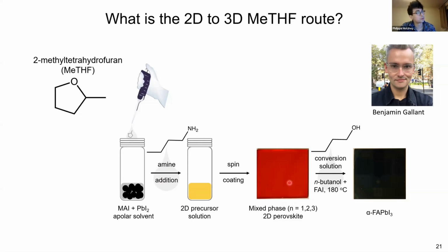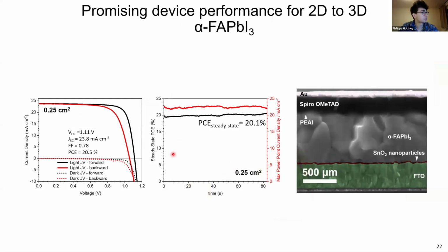So this is actually an image of this film. And then only after we convert it with the conversion solution of butanol and anneal it at 180 degrees for 1 hour or 1.5 hours, we get the alpha phase of FAPbI3. So we find there was no methylammonium left inside of it, and also very little butylammonium. And this route allowed her to make some nice devices. So here on the small area, you see that the devices reach the JV scan efficiency of 20.5 and a steady state efficiency of 20%. And here you see cross-sectional SEM in an NIP structure, but we also made them in a PIN structure.